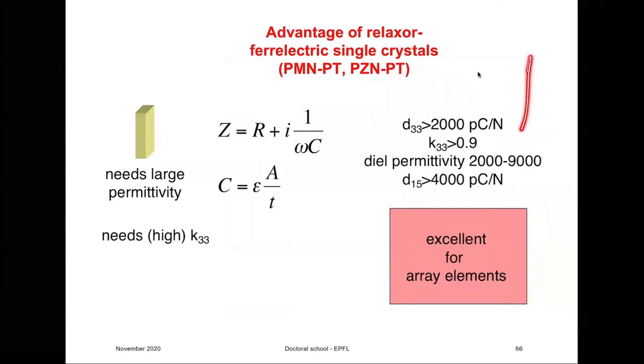So single crystals of relaxer ferroelectrics are very good here for some of these array elements. They have very large D33, very large K33, which reaches 0.9. So the energy that is transformed from input to the output energy can be 80%. You can also use them in a shear mode in which they are at some cuts very large D15 coefficients.